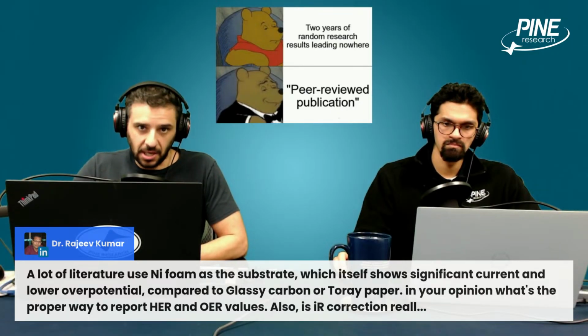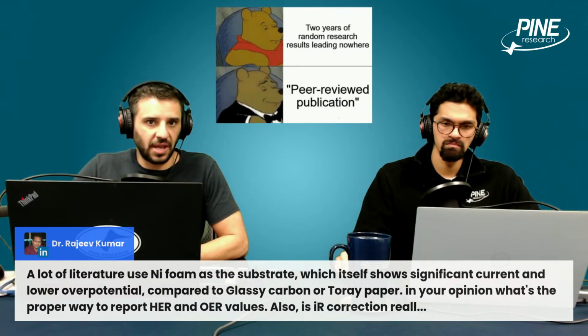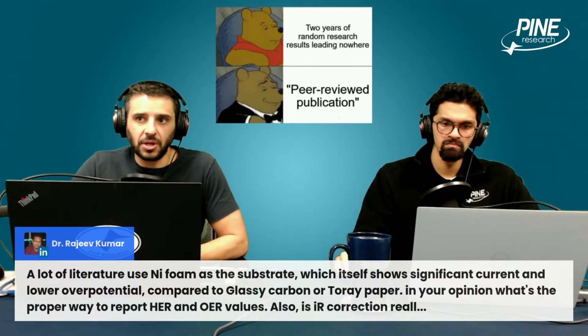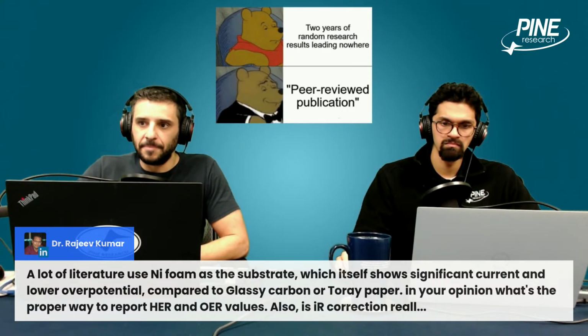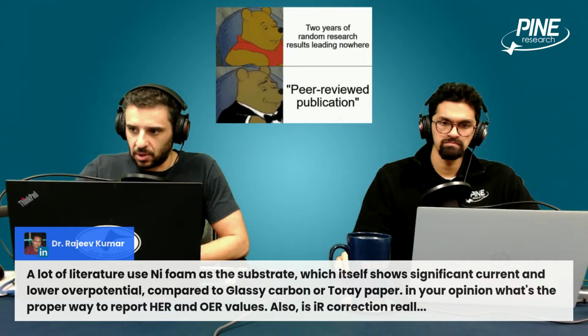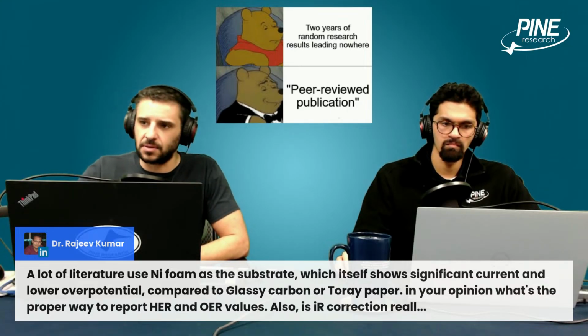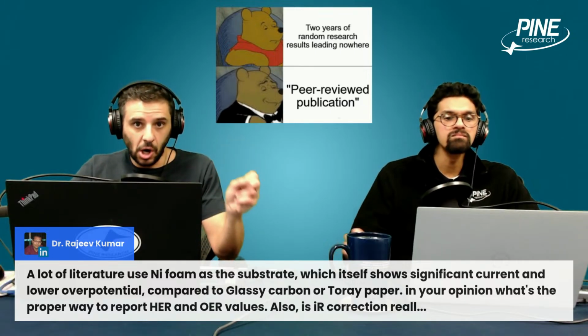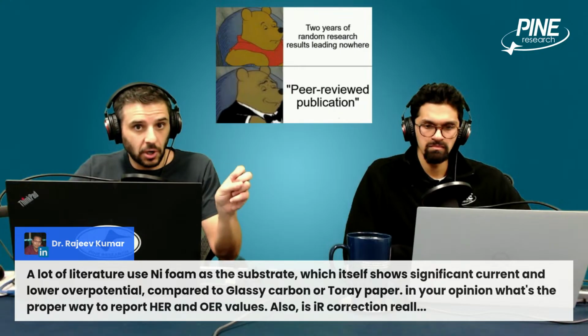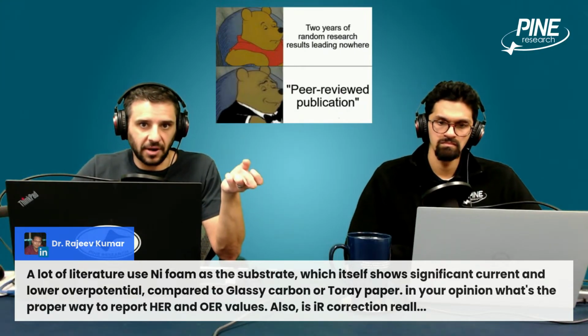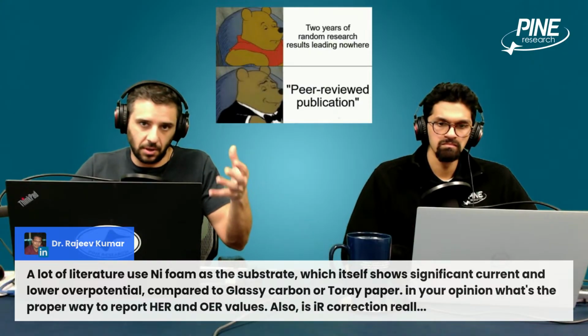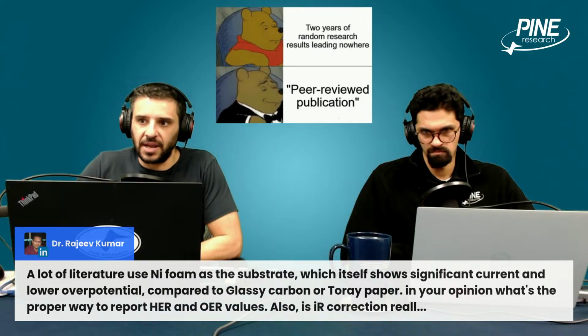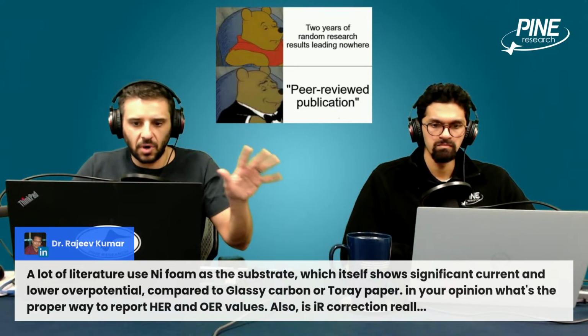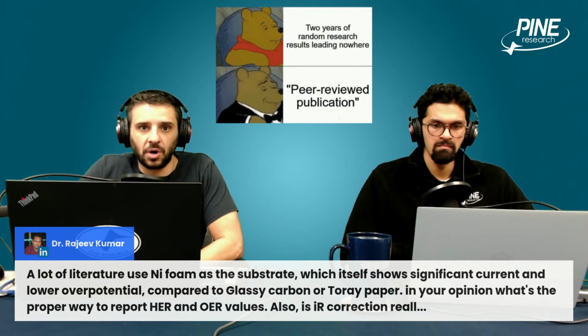is completely covered. Like if you're doing electrodeposition, if you're doing a physical deposition, spray coating, whatever, however you're covering the nickel foam, right? And this would be done either microscopically or with elemental analysis of some kind, EDX or something of that nature, to determine that there's no nickel exposed whatsoever. This is really difficult, especially because it's a foam and it has a really high surface area, and all the little nooks and crannies, did you really coat everywhere with your catalyst of interest, right? Sometimes dipping it into maybe a viscous solution can kind of work,